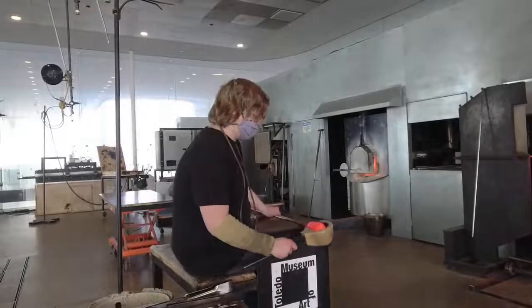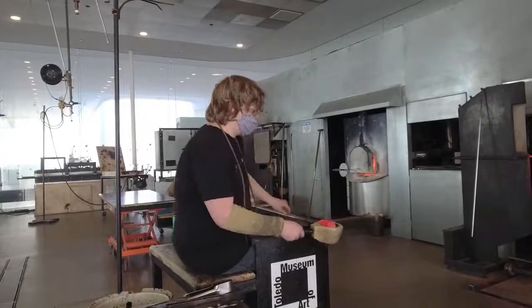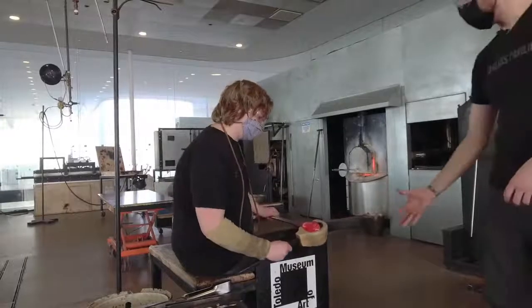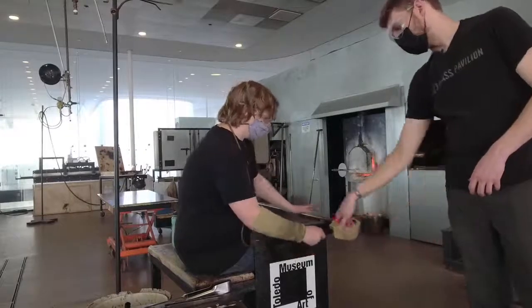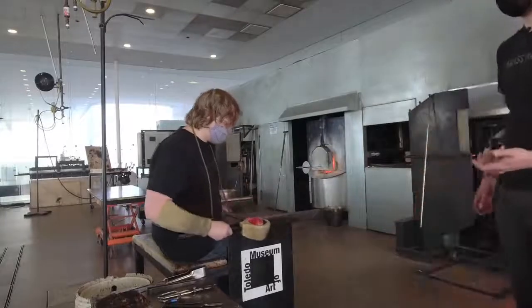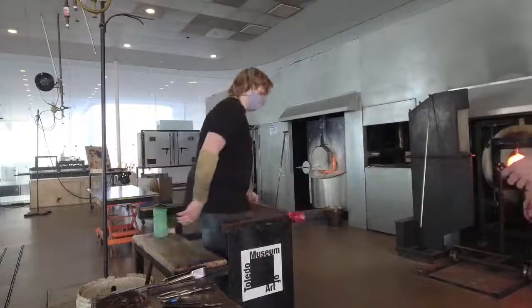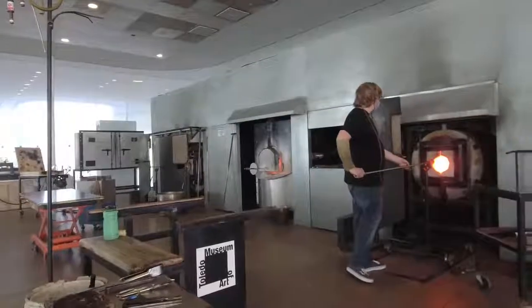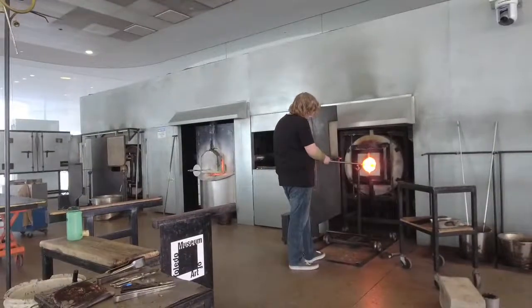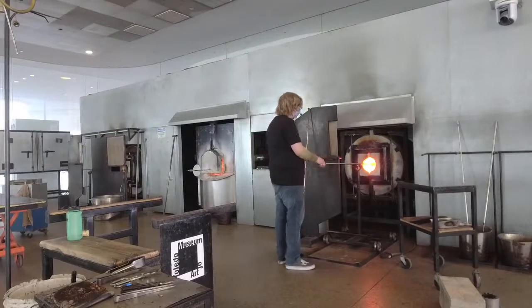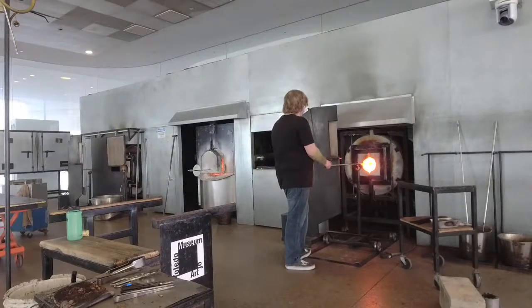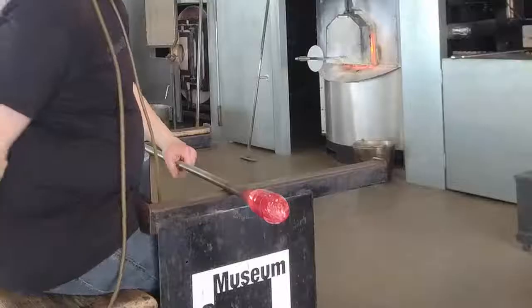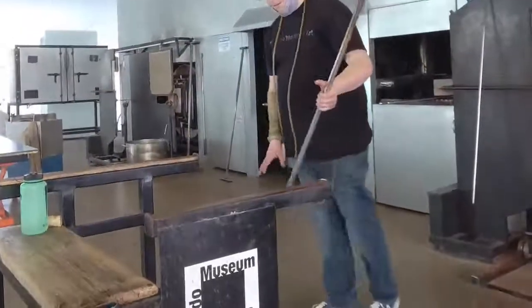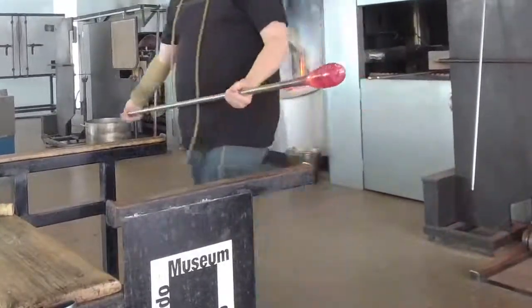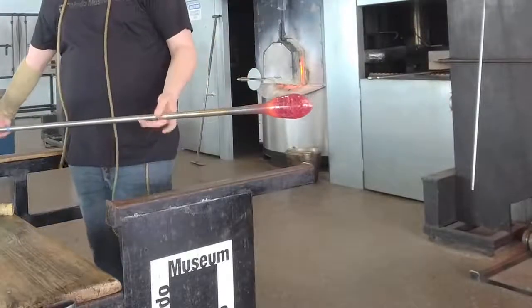This blocking tool is just a couple bits here. We have a carved wooden spoon here, and then we have a carbon fiber handle. Normally it would be a wooden handle, but we've opted to switch to carbon fiber here at the Glass Pavilion. But we use a lot of different kinds of fruit woods, primarily cherry, because it has a tight grain pattern, a low sap content. It's very absorbent to water, and it doesn't ash as much as some other woods. So it's just perfect: when something superheated comes into contact with moisture, it's going to instantly vaporize it and create a layer of steam. And that's what's going to give us this nice shape here.